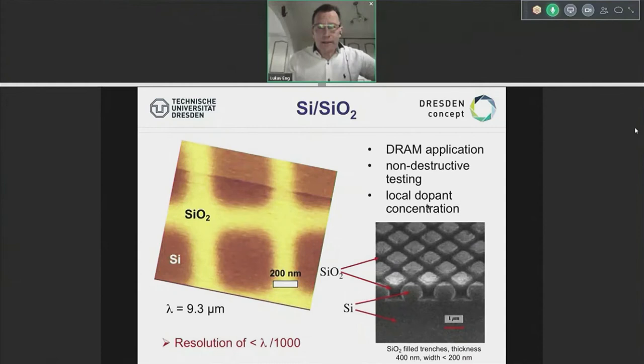as you see here. Electron microscopy is bad because it cannot confound between silicon dioxide and silicon, because the silicon dioxide is not even visible for the electron microscope. You see here all these dashes. It's not voids, but they don't see it.